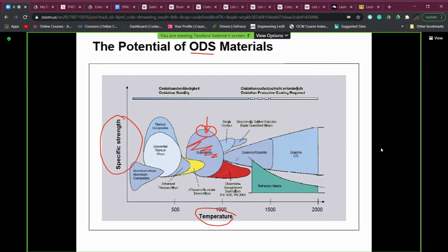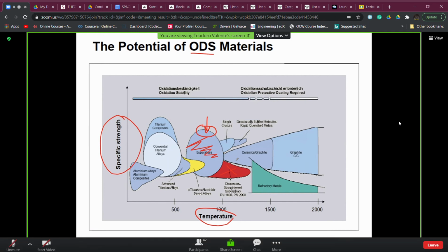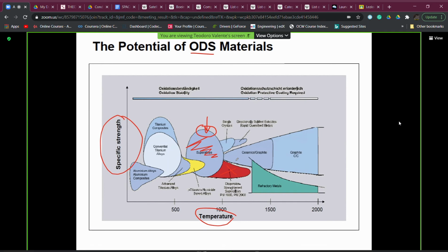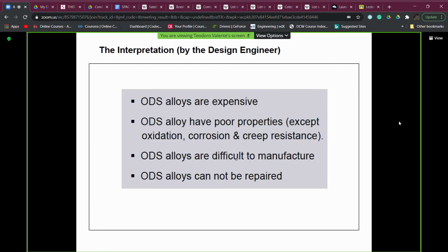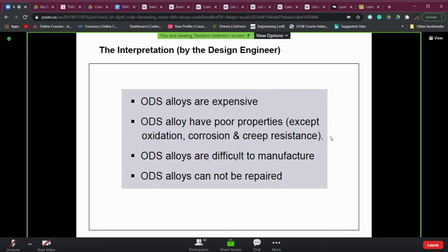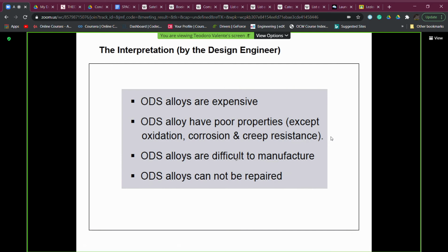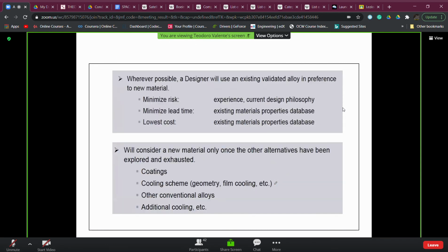But nevertheless, the ODS in some cases can be met, and in other applications, as I will tell you, they are used. They are expensive materials because they need a special fabrication technology, and except for oxidation, corrosion, and creep resistance based on dislocation movement, as I told you, their other properties are lower than or comparable to nickel-based superalloys. And then they have some other drawbacks: complexity of manufacturing. They cannot be repaired because they are a solid solution of, for example, metallic-based alloys with an oxide phase.